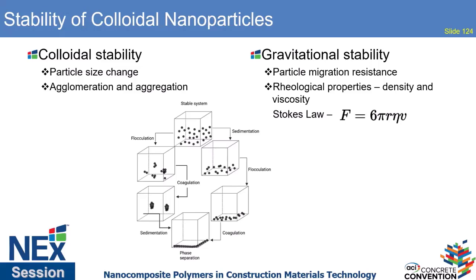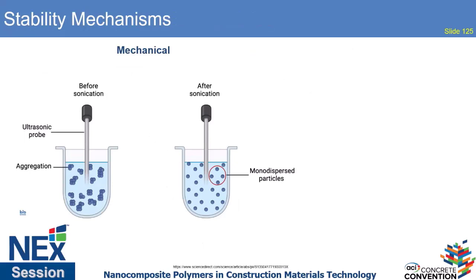Now, many times you can hear that you can achieve a colloidal stability even if you have gravitational instability, which is correct for a certain period of time. However, over time, if you have a concentrated amount of particles in a small space, they will start to flocculate and eventually they will coalesce and aggregate, and then you will get the phase separation. When we talk about stability, we talk about mechanical stability and we talk about chemical stability. Sonication has been a proven method for mechanical stability of nanoparticles.